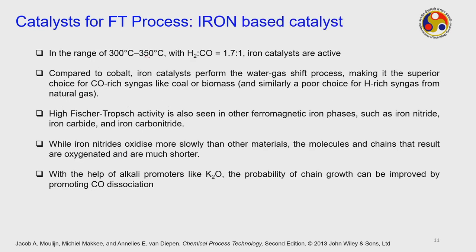So, in this range of temperature with hydrogen to carbon monoxide ratio as 1.7, iron catalysts are active. Compared to cobalt, iron catalysts perform the water gas shift process, making it the superior choice for CO rich syngas. So, what is the water gas shift reaction? Water gas shift reaction means CO reacting with H2O to form CO2 plus H2. Okay. So, this water gas shift will reduce the content of CO. So, it is a CO rich syngas, so it means it will convert CO to CO2 and H2. Such that you will have a choice for those feeds which have a high amount of carbon monoxide.